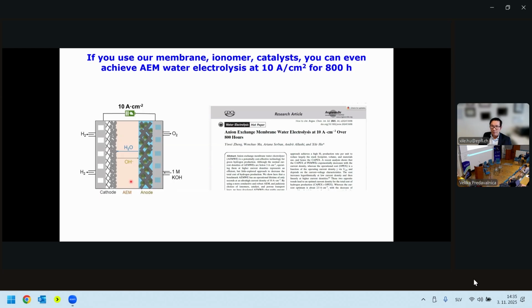And so if you use our membrane, you use our ionomer and catalyst, you can actually do good things. And so in this case, we saw earlier this year, we can actually achieve AEM water electrolysis at 10 amp per square centimeter for 800 hours, okay? To demonstrate that the material properties now are ready, okay? We can actually do really, really incredibly difficult conditions for this, okay?